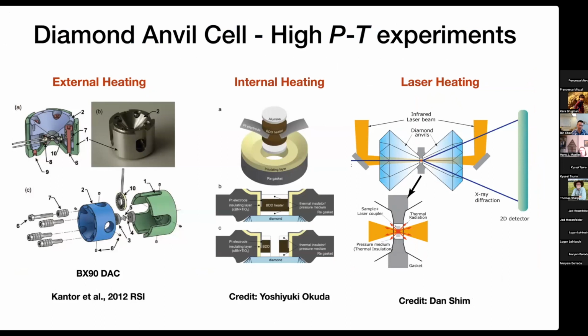For the diamond anvil cell, if we want to generate high temperature, there are typically three ways that we can heat up samples in a diamond anvil cell. One way is external heating, another is internal resistive heating. For external heating, we place a micro heater around the diamond, but for internal heating, we actually place the heater inside the sample chamber.